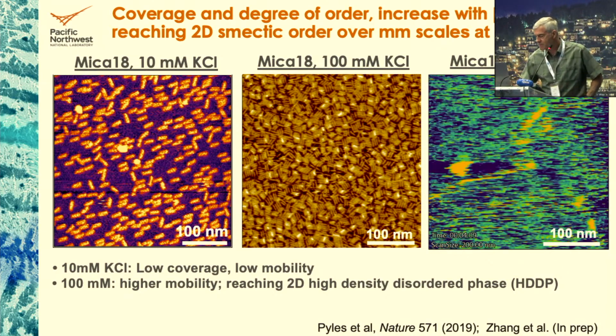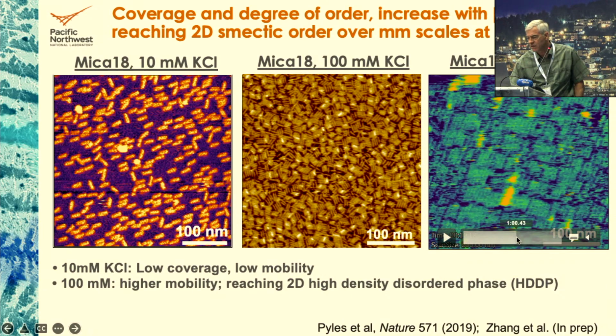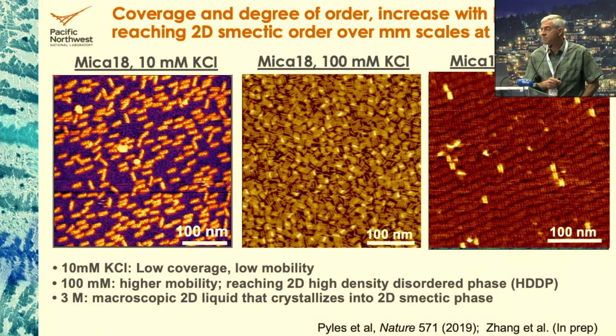But here's what happens. If you watch carefully as this goes on, you'll start to see domains appearing. But you'll notice that these domains only start appearing along one direction. They never show the other 2 directions. And the end state of this surface is really quite remarkable. It's a 2-dimensional smectic crystal with 1 billion proteins all co-aligned in rows.